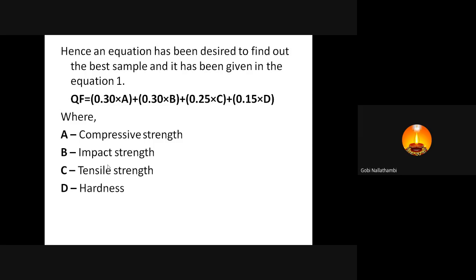So the weightage given for compressive strength and impact strength is similar, that is 0.3 and 0.3, and for tensile strength it is 0.25. But in case of hardness, it is 0.15, because the hardness values are almost equal for all the samples. But there is a huge variation between the compressive strength and also the tensile strength, even impact strength. So to obtain the best suitable input parameters, we have to give weightage for that property.